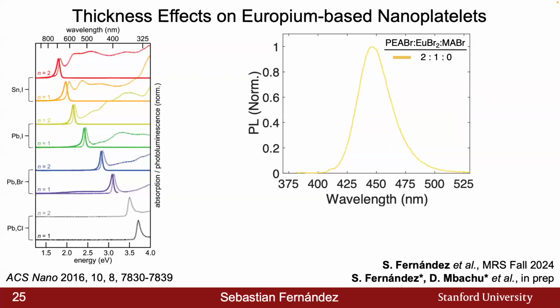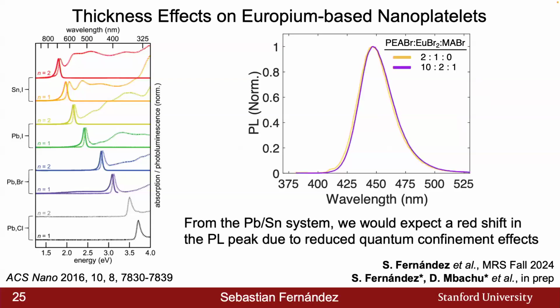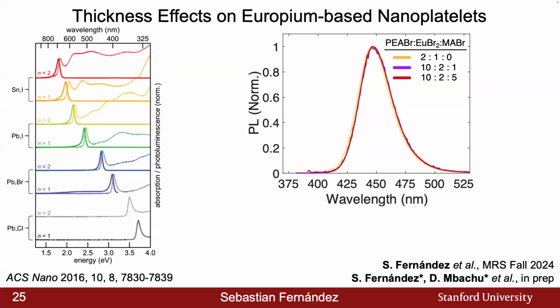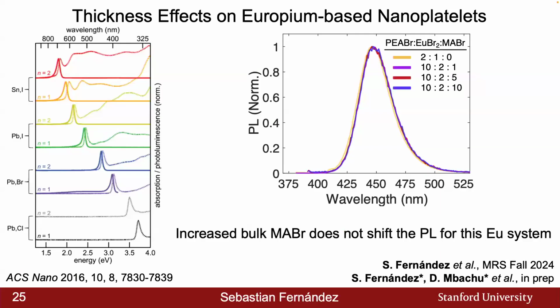By looking at the previously reported 2:1:0 ratio, we should get the N=1 nanoplatelet, which has a photoluminescence peak at around 450 nanometers. And then when we look at the 10:2:1 ratio from this system, we should see some sort of redshift. But we don't see that here due to reduced quantum confinement effects. If we expand further, adding even more bulk cation, we see that this bulk methylammonium bromide doesn't shift the photoluminescence at all.